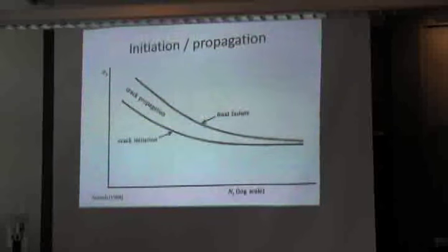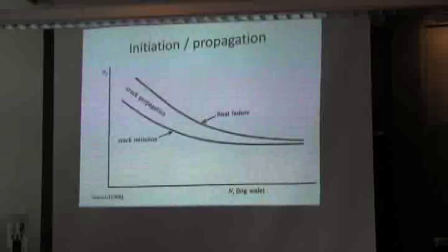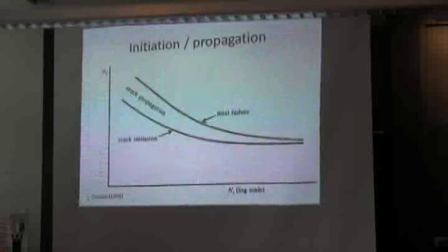The other aspect of the stress strain curve, and we're going to tie back here to, remember I showed you the fracture surface of some plastics where it started in the center and then it popped. And I said that it didn't take a whole lot of time to start many cracks around a very small particle in there. What happened for that example is we were relatively high in stress. So say we were right about here on the vertical where it says crack, and therefore from the beginning we had a little bit of propagation. They were very small cracks, but then they were growing like fingers and merging together, becoming a big crack, and